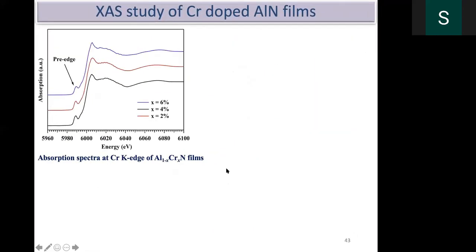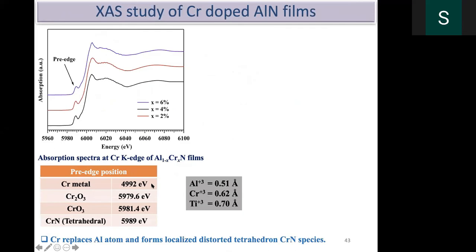Again, we did the X-ray absorption spectroscopy. Interesting thing again here, oxygen did not form. This pre-edge is the one which will tell you whether the nearest neighbor is chromium-nitrogen, chromium-oxygen, or chromium-chromium. From this peak, we understood that only chromium-nitrogen formed, not chromium oxide, chromia, or pure chromium metal. And chromium replaces the aluminum atom, similar to the titanium case. That's what we have observed.